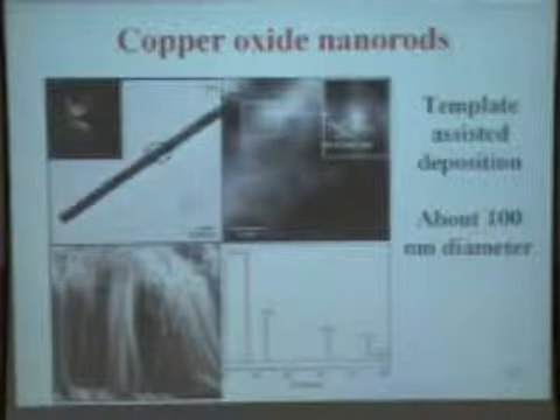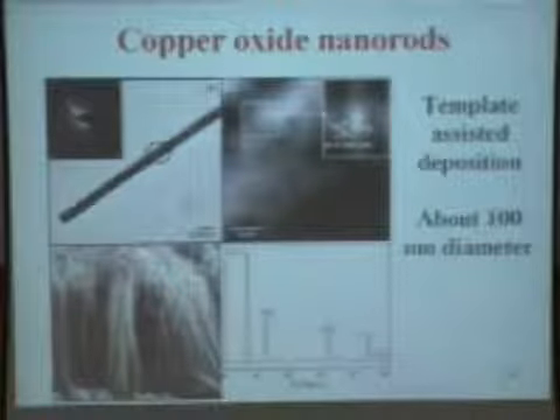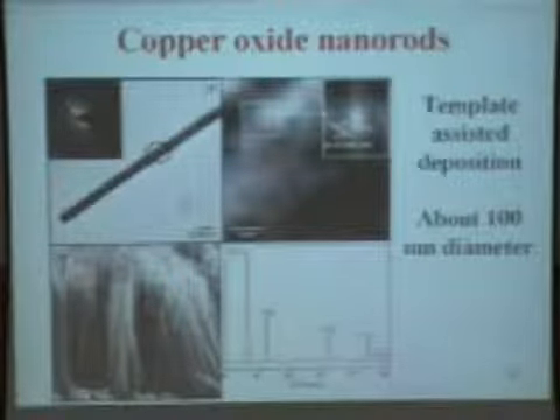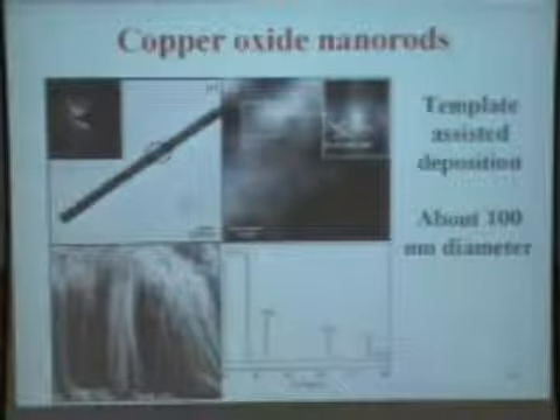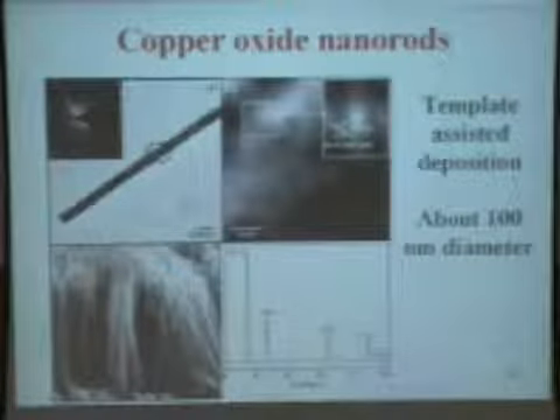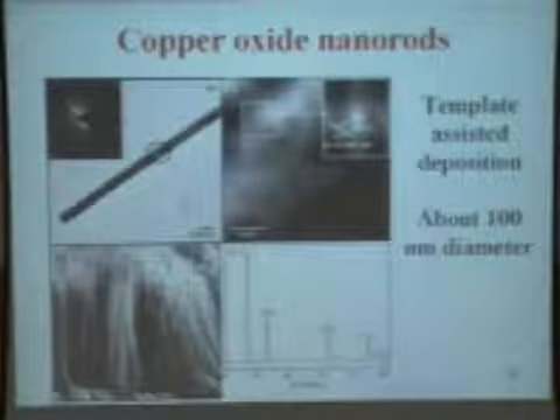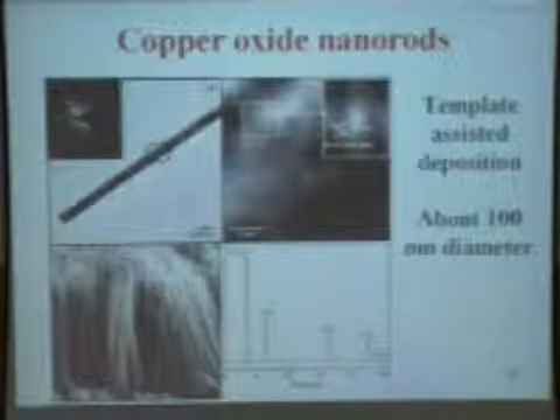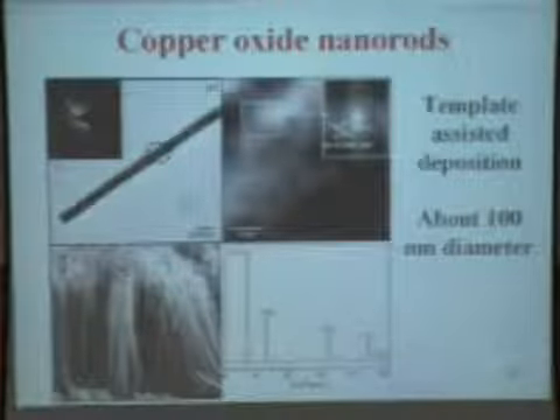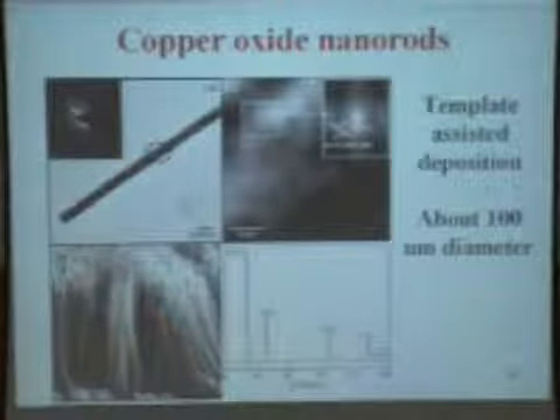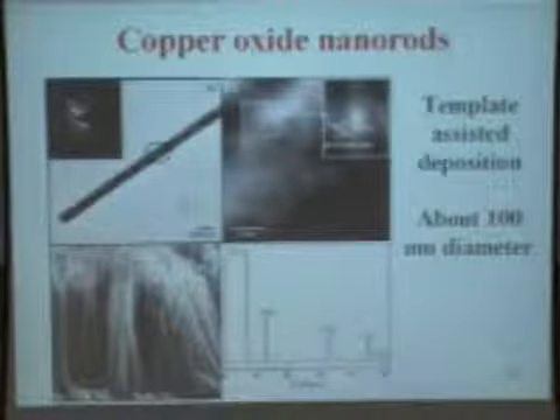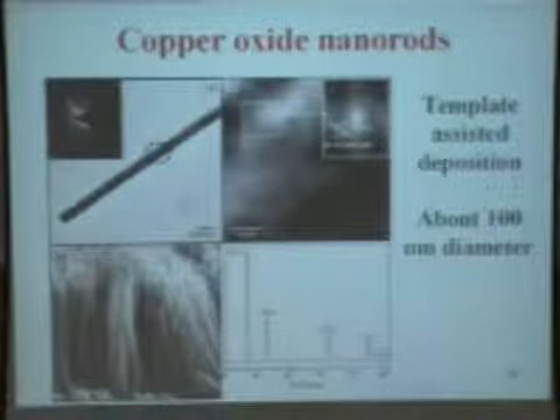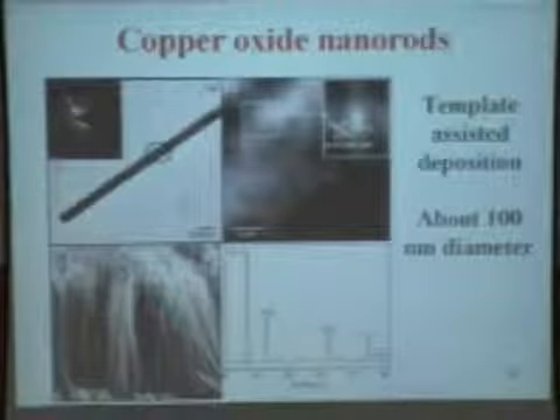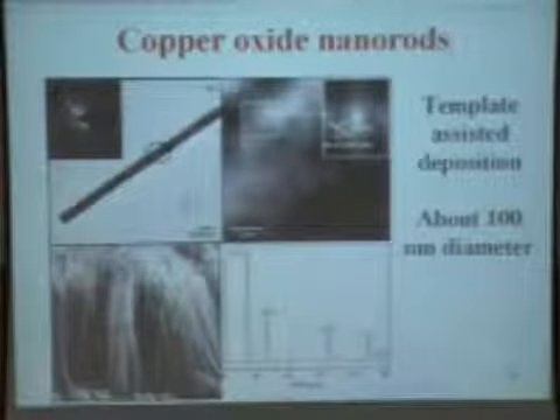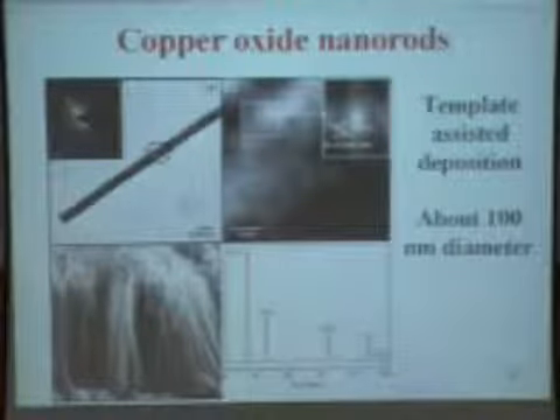What we thought was that we should use nanorods. These are copper oxide nanorods made by what is called a template-assisted deposition method, which we were discussing during lunchtime. You have an alumina template, you electrodeposit into the template, and then you remove the template, and what comes out are these copper oxide nanorods. Their dimension here is around 90 nanometers, but it is possible to go from 30 nanometers to 90 nanometers by this method. And you can have really standing nanorod structures.